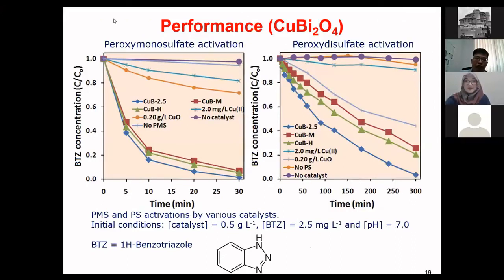We use it for benzotriazole removal in water, and we found that, of course, this catalyst works very well. In fact, we compared with other different types of catalysts, and the one with the fancy morphology gave a better performance compared to others. And of course, when we look at the leaching, this is a very important issue. Catalyst leaching is relatively lower compared to the copper ferrite, the copper ferrite that we developed initially.